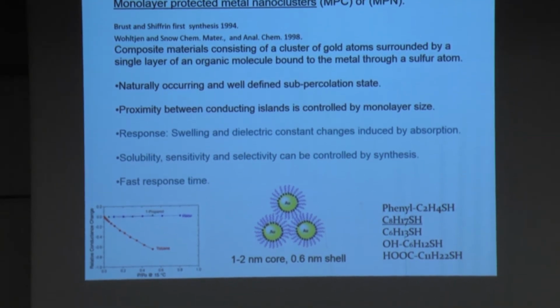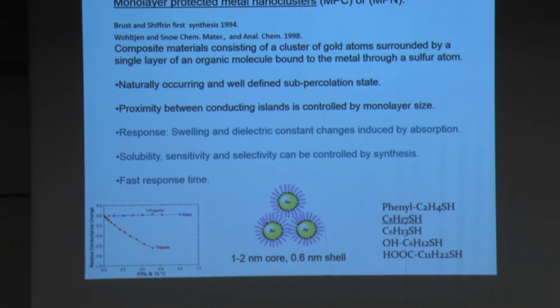For example, if you have an octanethiol, like here, the shell size is about 0.6 nanometers, and the distance between the two islands is somewhere between 0.6 and 1.2, because sometimes they overlap. In any case, these small distances cause the electrons to tunnel. I mean, electrons can tunnel across these distances, and they can also hop between the islands, okay?